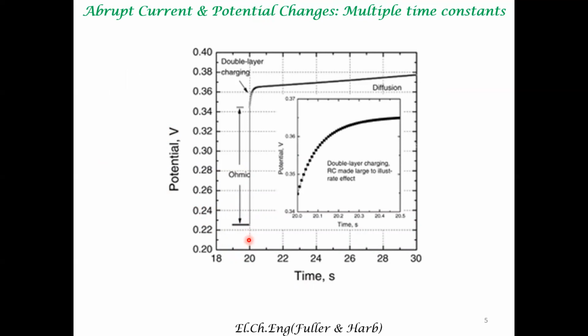So we can decompose this potential into three components. One is due to the sudden increase in current, the ohmic potential. And then at short time scale, because there is a sudden change in current, it involves a rather large capacitative current. So this is being blown up here. So in this very narrow region, between 20 seconds and 20.5 seconds, capacitative currents do play a role. Okay, that is the only time they do play a role. But after that, there is not much change in potentials.